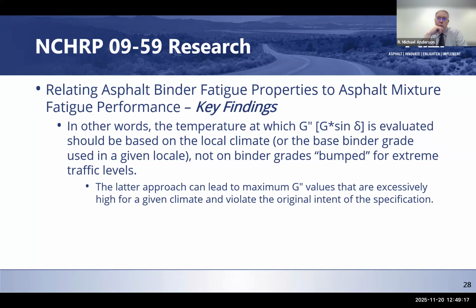We've done a little bit of work correlating between the two. We can see a strong correlation between the B component, if you will, from the linear amplitude sweep, which is the slope. That does relate pretty strongly to what we would see when we look at things like delta Tc or R value, which is not a surprise, perhaps, but there are some relationships that have been seen, yes.